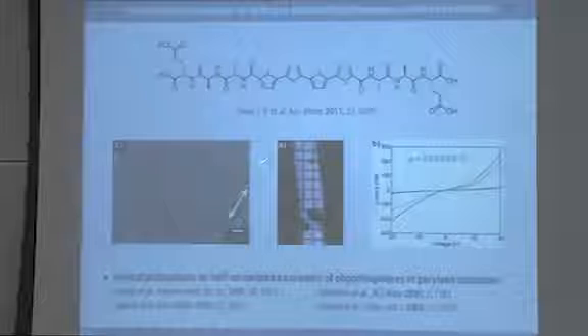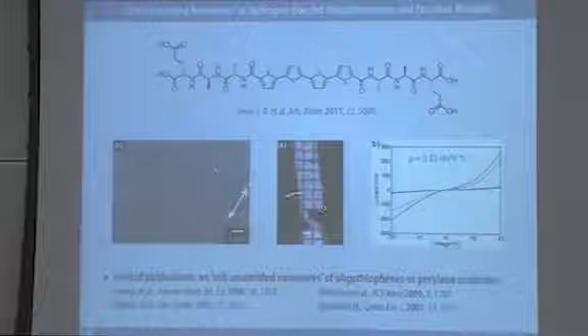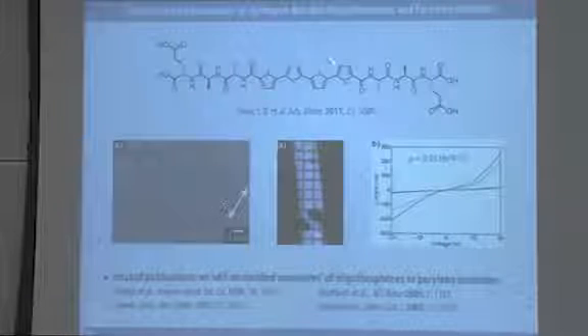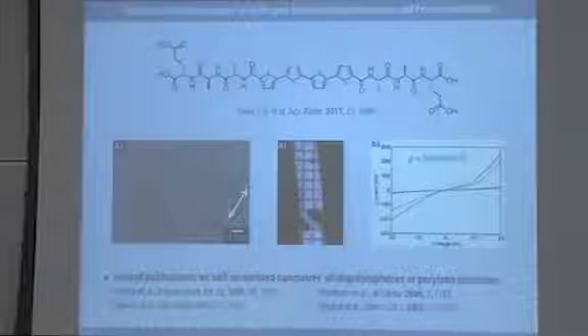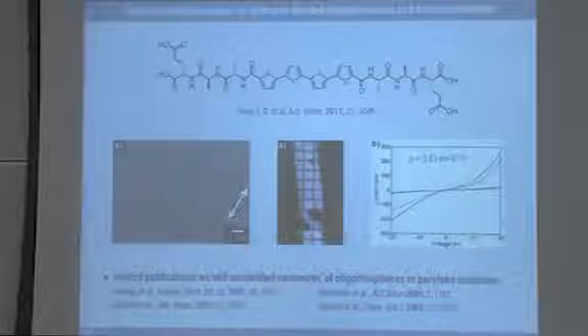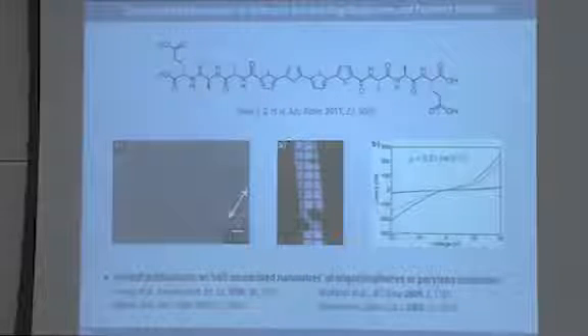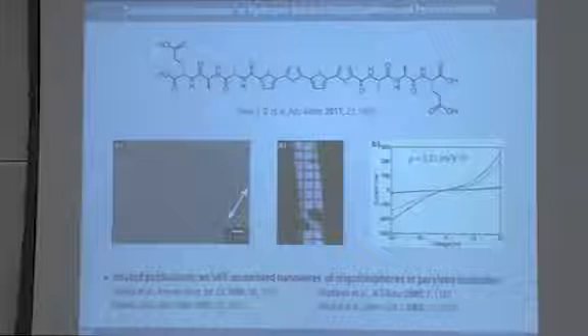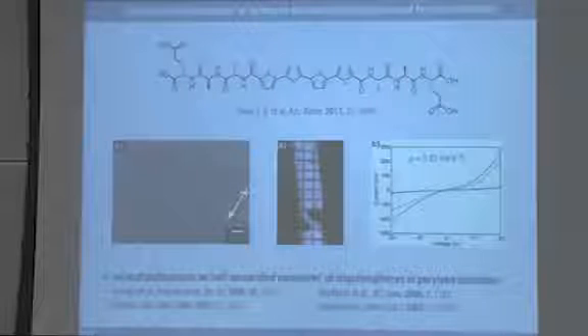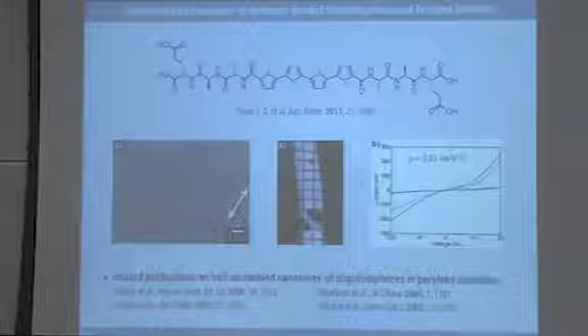But even in this case, in the end they make nanofibrils, but they measure the conductivity of a bulk thin film of microfibers. So the thickness of these fibers is much larger than the nanowires they originally claim. It's been processed from water. There are some strangenesses in the IV curves, and I think that it is fair to say that this molecule conducts. But what is actually the nanostructure that is responsible for conduction, and what is the charge carrier species, is actually not well understood. In this regard, things might be a little better in the case of anisotropically grown crystals,